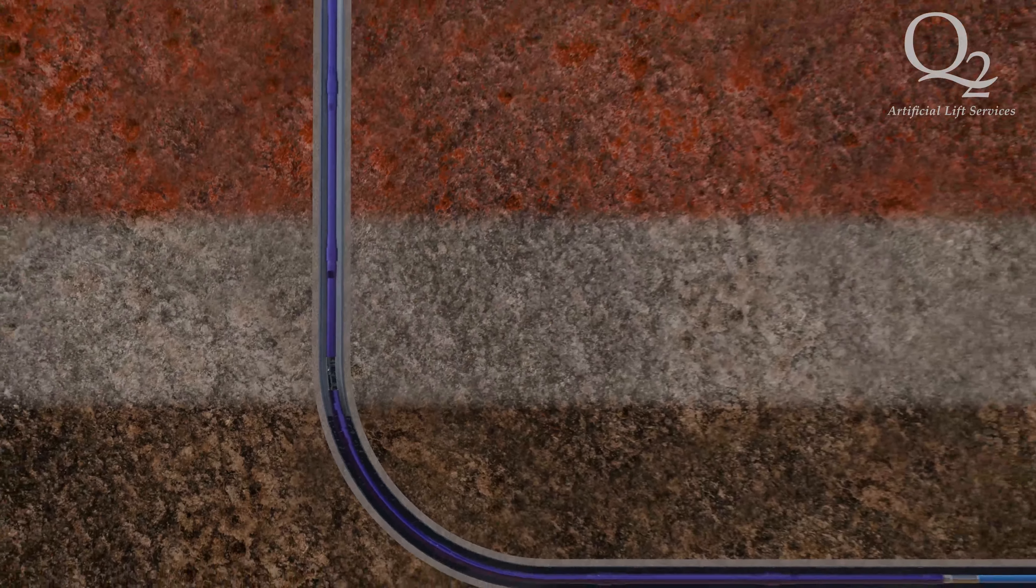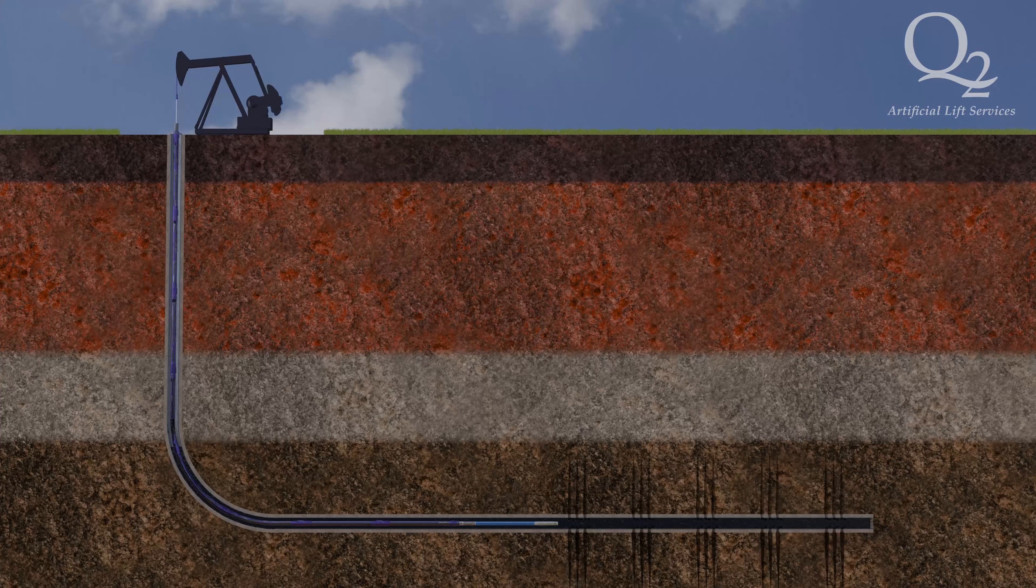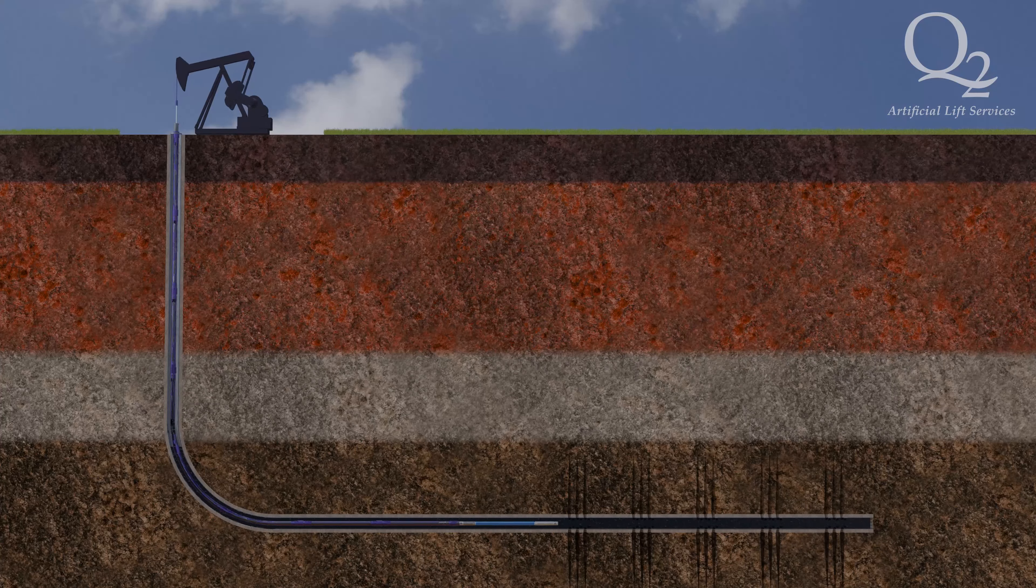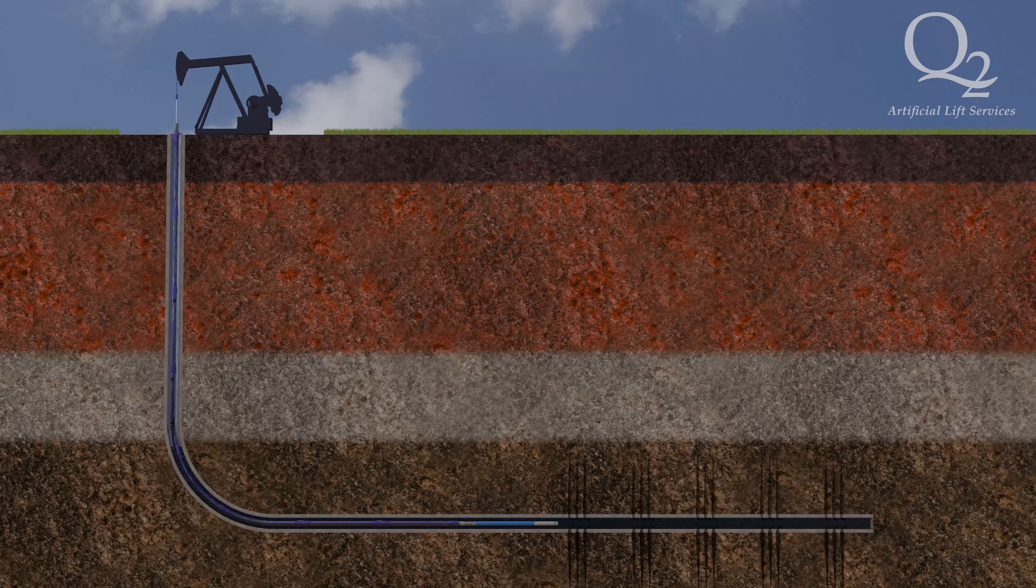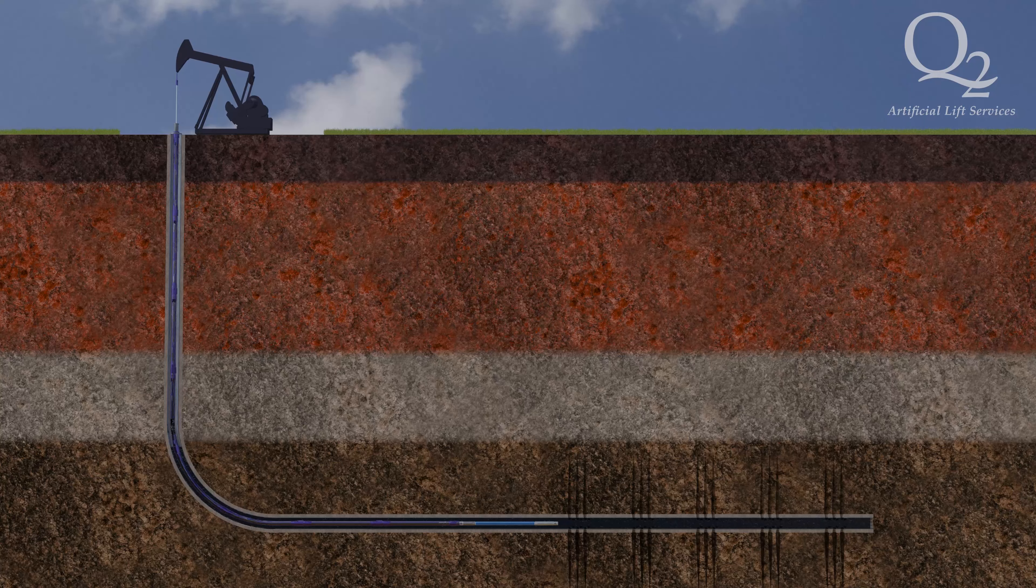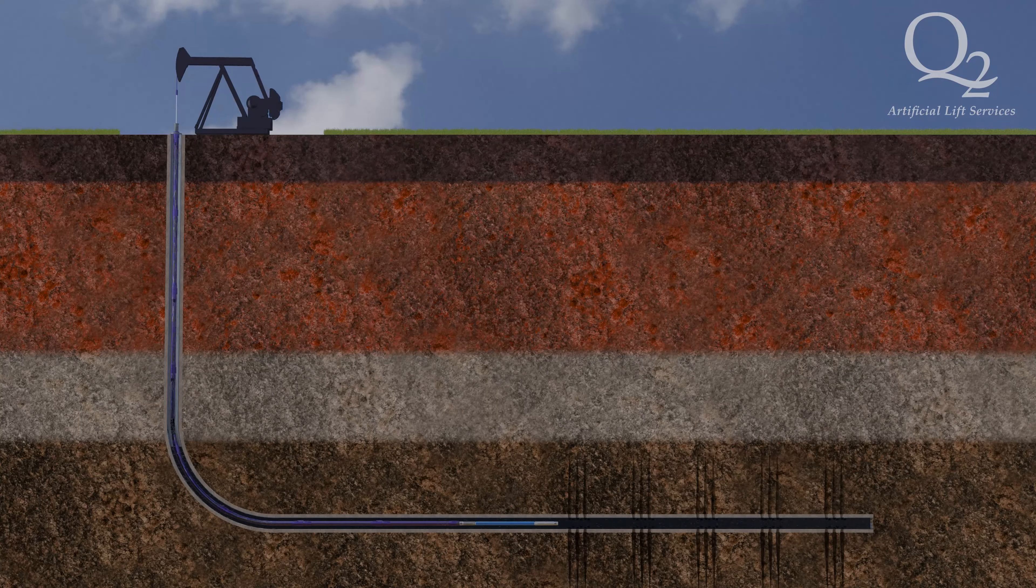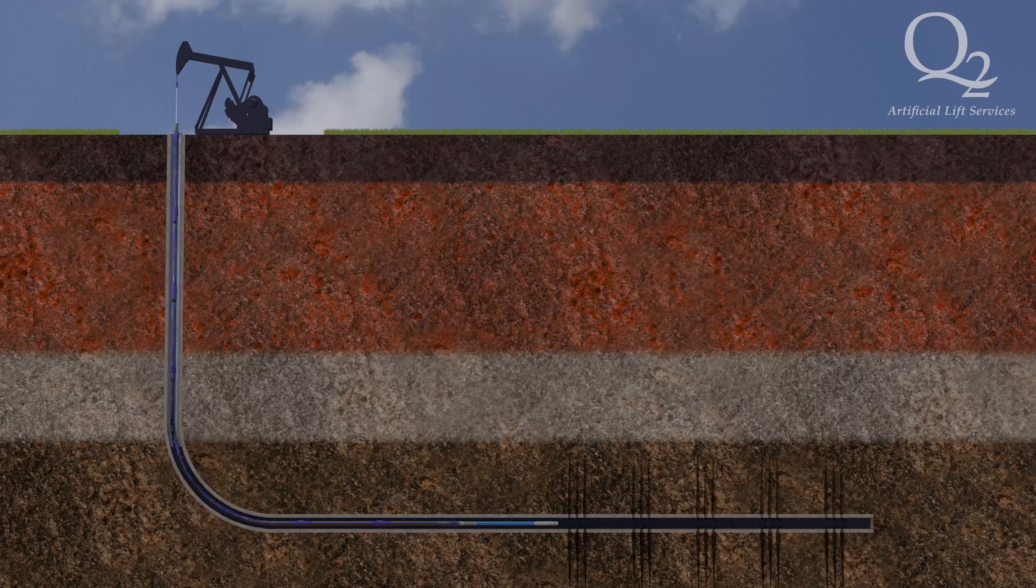Q2's composite plated tubing, CPT, is based on the combination of electroplating and electroless plating, adding non-soluble particles such as ceramic particles into a bath so that the particles can be deposited with the plating process.